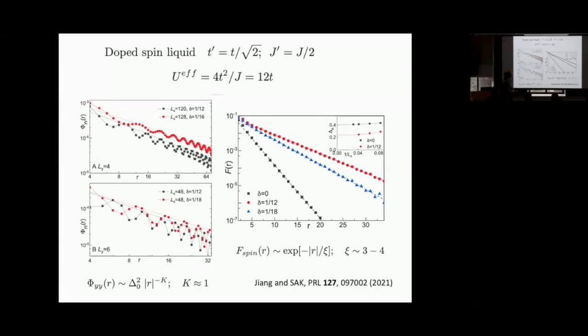Here you see the spin correlator, and you see that this falls exponentially. This is the undoped system, which, as I said, is a quantum paramagnet characterized by short-range spin-spin correlations. Here are the 1/12 doped and 1/18 doped systems, and these both have slightly longer spin correlation lengths, but ones that are more or less continuously connected to the spin correlation length of the undoped system.